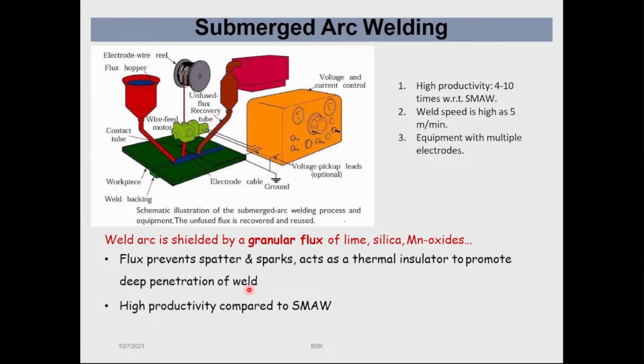So same thing. Okay? High productivity compared to shielded metal arc welding, right? So it has a higher productivity because it has a deep penetration. The weld has good quality, good penetration. You can see high productivity, 4 to 10 times with respect to shielded metal arc welding, and weld speed is as high as 5 meters per minute, right?